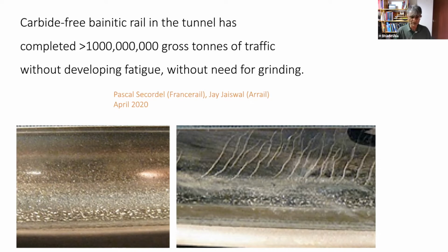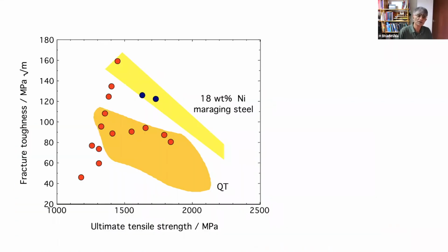Now, the structure that I showed you is very versatile. You can change the scale. We had plates which were 1/4 of a micrometer in thickness. You can make them coarser or finer by controlling the transformation temperature. So there are many variants of that material, and there's even variants which compete with maraging steel, but are much, much cheaper. So this is a plot of fracture toughness versus tensile strength.